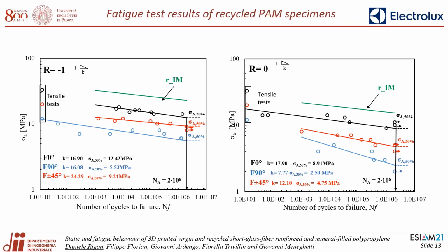These slides show the fatigue test results of recycled materials produced by additive manufacturing, for R equal to -1 on the left and R equal to 0 on the right. More precisely, in this figure, the black points refer to the F0 specimens, the red ones to the F45, and the blue ones to the F90 AM specimens. For comparison purposes, the previously seen fatigue curve for recycled injection molded specimens is reported for both load ratios in green.